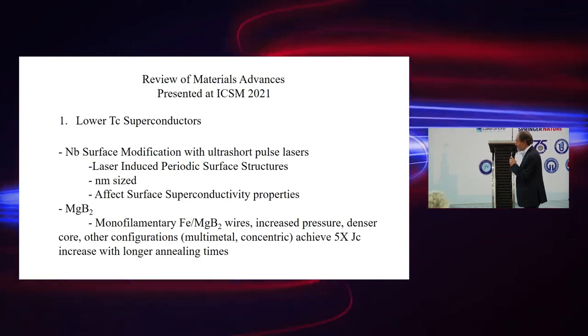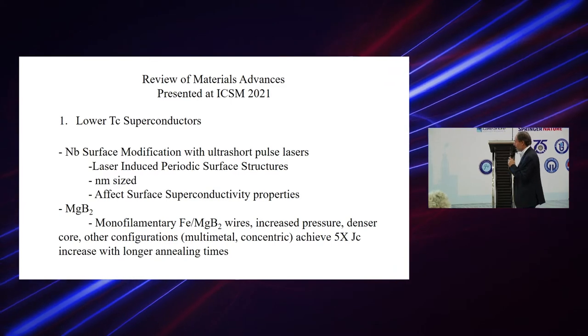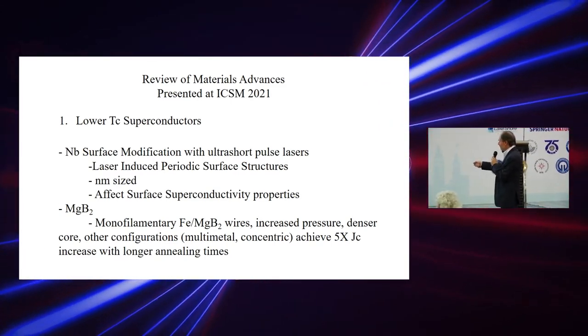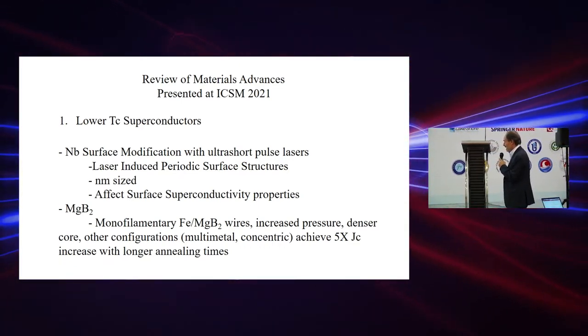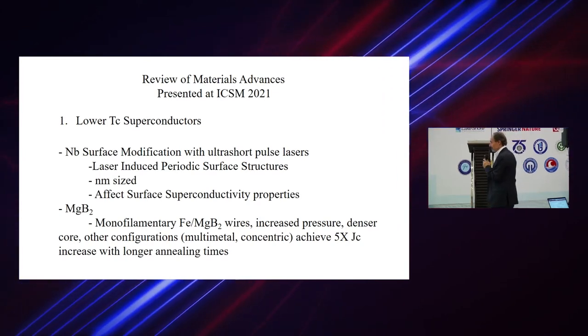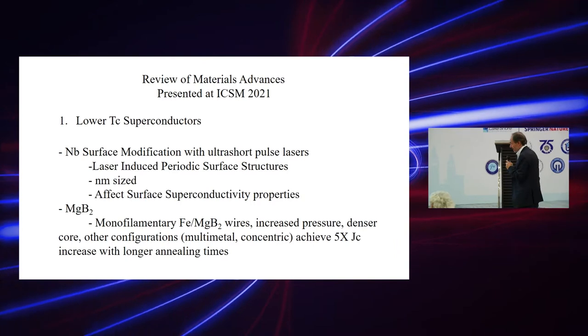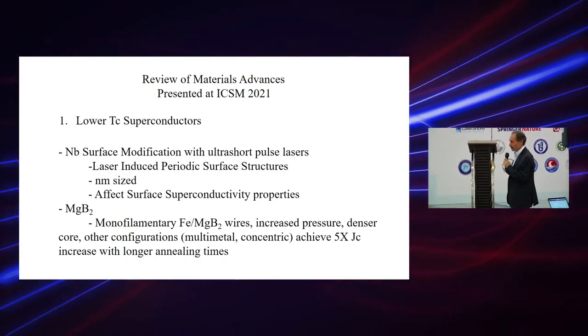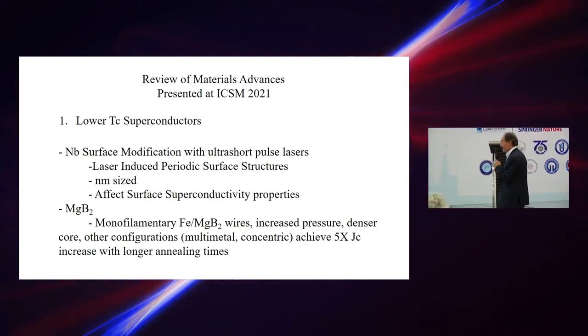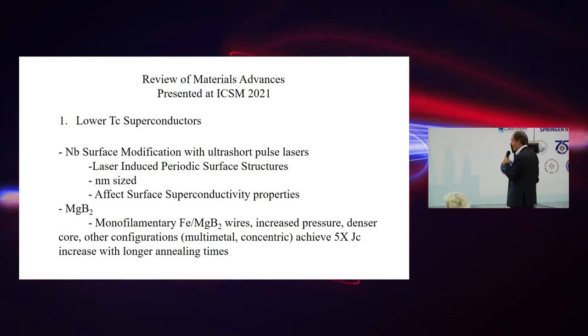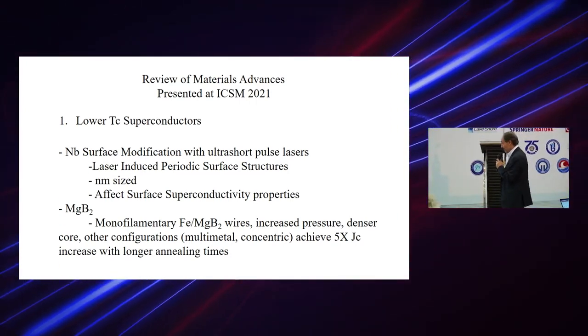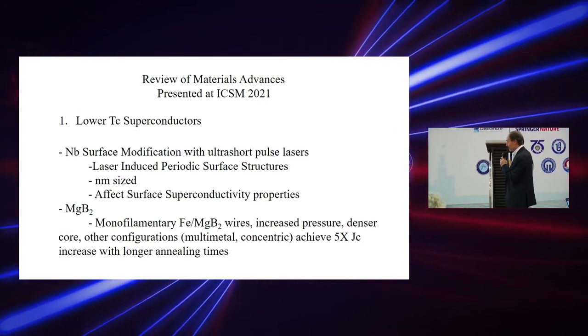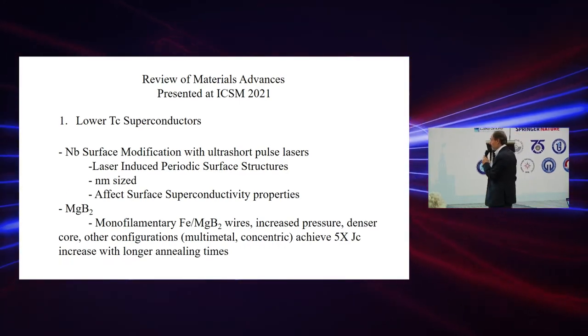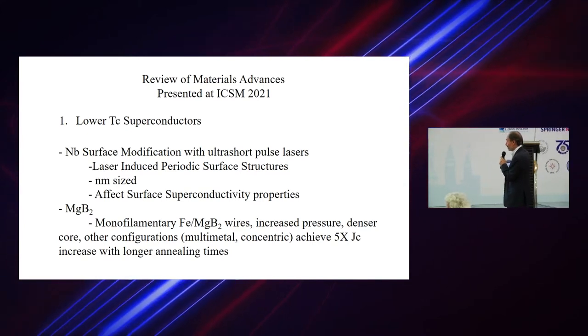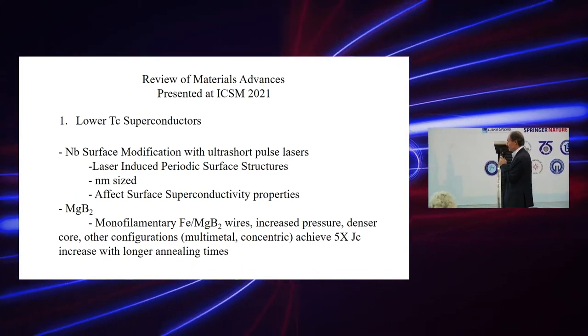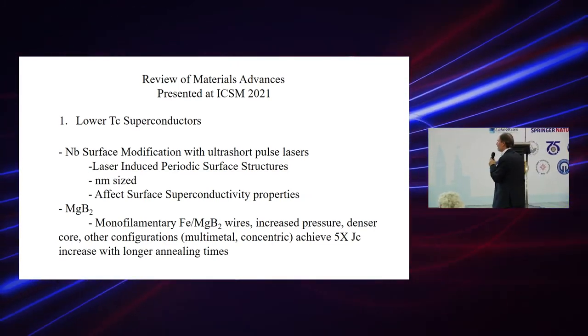First, what I would call lower TC superconductors. There was a presentation on niobium surface modification with ultra-short pulse lasers, which generate laser-induced periodic surface structures, which are nanometer size in period, usually ranging from approximately 200 to more than 500 nanometers. These are very interesting. They're very highly ordered over a large area. They affect surface superconductivity properties, and from other published work, they also affect pinning and levitation forces. So I think this is an upcoming processing route, which will be very interesting in probably most types of superconductors. And it can be scalable.